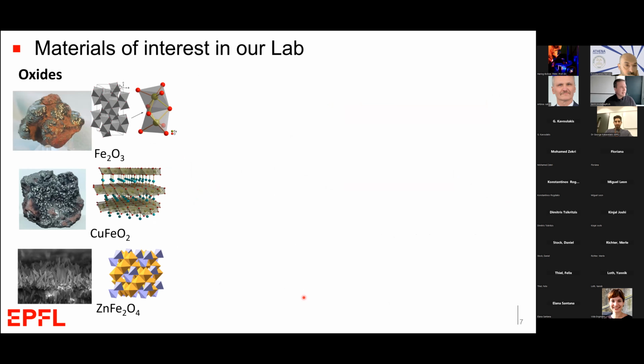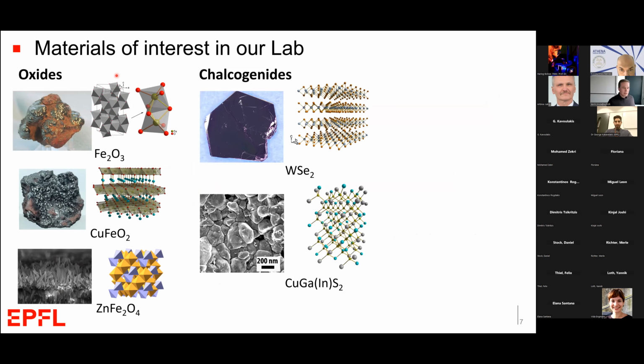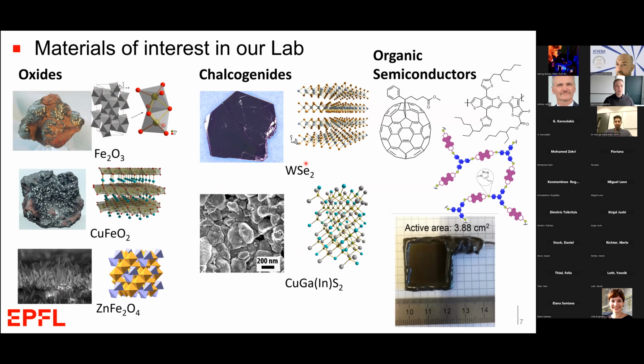So what materials are of interest for this direct semiconductor liquid junction, either in a photocatalyst or in a photoelectrode? Well, there are plenty. The field is looking at oxide materials, not just these, but bismuth vanadates and other ternary oxides are quite popular right now. Chalcogenide materials, like the CIGS type materials, tungsten diselenide. And our lab has some special experience with organic semiconductors and looking at these for a prospect in this direct solar fuel production reaction.